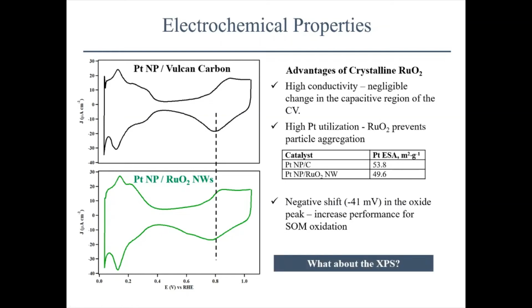So an interesting question that we had to ask ourselves was, what about the XPS? The XPS showed that the two peaks were overlaid, yet we see this negative shift in the oxide peak. So what this tells us is that there is an interaction there. The ruthenium oxide is impacting the electrochemical properties of the platinum, but the effect is relatively subtle, and perhaps it's subtle enough that we can't even detect it in XPS, meaning that we're not doing a bulk change of the platinum itself, the platinum nanostructure, but perhaps at the interface we are getting enough of an effect to be able to detect it in the electrochemistry.